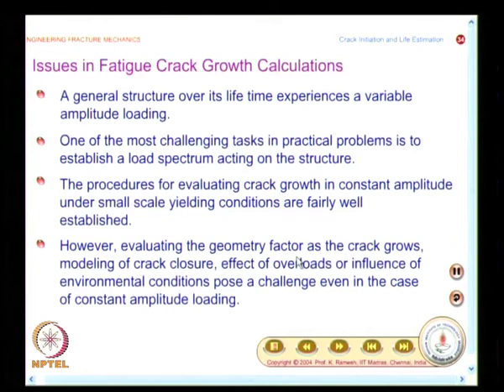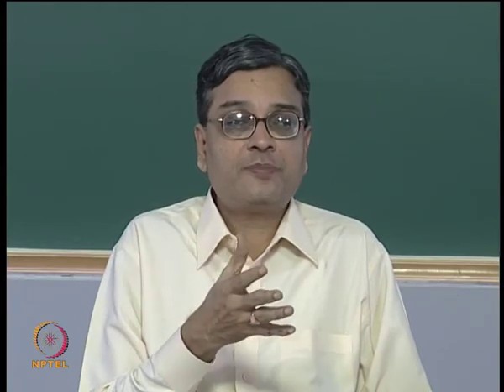Evaluating the geometry factor as the crack grows. See, we have looked at stress intensity factor as K equal to beta times sigma root pi a, and I said beta is a parameter which depends on the geometry of the specimen. And when you have a crack and the crack starts growing, a by w ratio keeps changing. When a by w ratio keeps changing, you will have to find out the stress intensity factor using several terms in the series. So, hand calculation is ruled out.